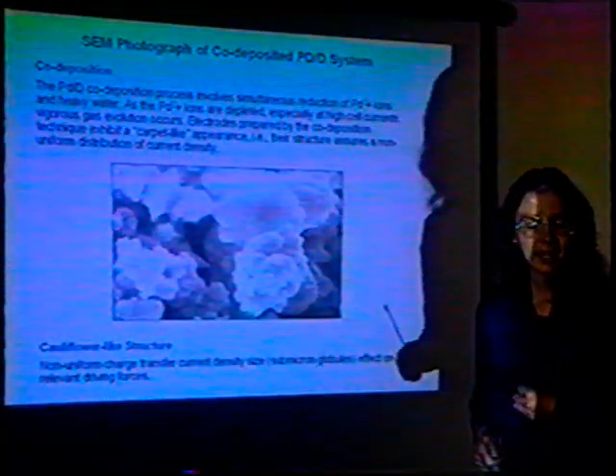Now, we have not done any calorimetry of the palladium deuterium system ourselves, but we do measure the temperature of the cathode and the solution temperature, and we've always found that the temperature of the electrode is 2 to 3 degrees hotter than that of the solution, indicating to us that the heat source is the electrode and not Joule heating. While we have not done calorimetry, Mel Miles at Naval Air Warfare Center Weapons Division has done so. He has run 3 cells, and he has achieved excess power every time. His excess power ranges anywhere from 100 to 400 milliwatts.